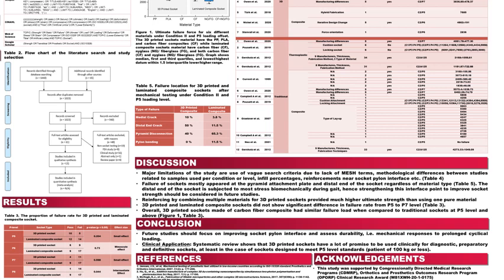For table 3, we also investigated the proportion of failure rate. Here we couldn't see any significant difference between 3D and laminated sockets from P5 to P7 load level. However, at P8 load level, the laminated socket had a lower failure rate than the 3D printed socket. And we also found that there was an intermediate effect on this failure rate.